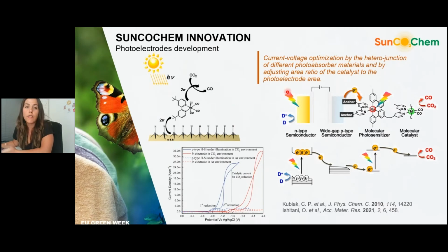So how SunCoChem is addressing those challenges in terms of material development to obtain those target objectives. In terms of photoelectrode development, the photoelectrodes are the core engine of the process, because they provide the sufficient current and voltage for the reaction to take place. In the literature, you can photoelectrochemically reduce CO2 to CO quite well in both homogeneous and heterogeneous systems. For instance, a rhenium catalyst combined with p-type silicon-based semiconductors can decrease the photovoltage needed for CO2 reduction to CO, showing good turnover frequencies of the catalyst.